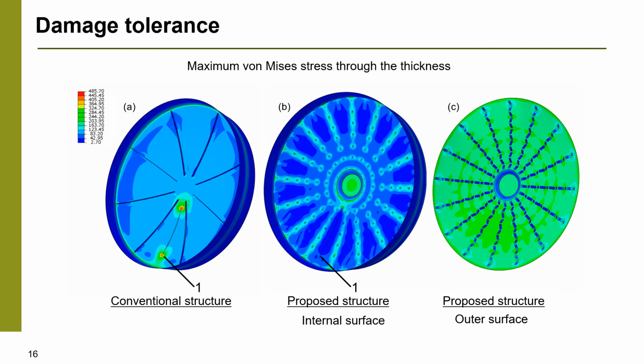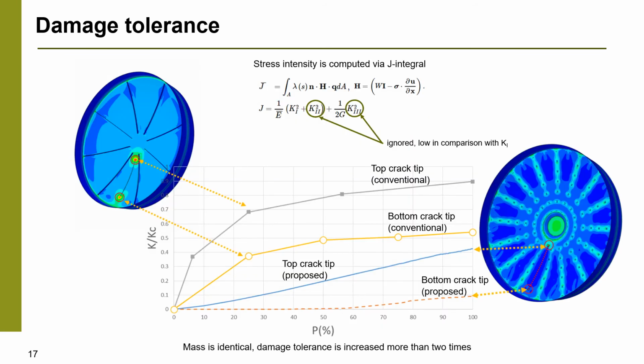For the modeling of the crack, we simply use disconnection between mesh nodes, and as you can see now, the crack causes much higher stress values for the conventional structure. Abaqus software allows us to compute the J integral for the contour over the crack tip, and using the J integral we can calculate the stress intensity factor. Here we assume that the first mode